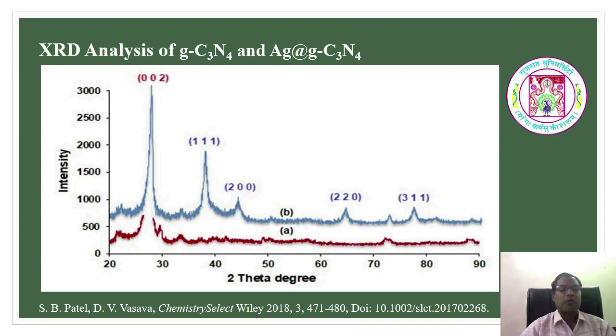The strong XRD peak at 27.50 originates from the 002 interlayer diffraction of the graphitic-like structure, having good agreement with the reported data. The X-ray diffraction displayed Bragg's peaks at 38.43, 44.08, 64.66 and 77.40, confirming the 111, 200, 220 and 311 facets of the face-centered cubic symmetry of the silver nanoparticles pattern, and that is also compared with the standard pattern.